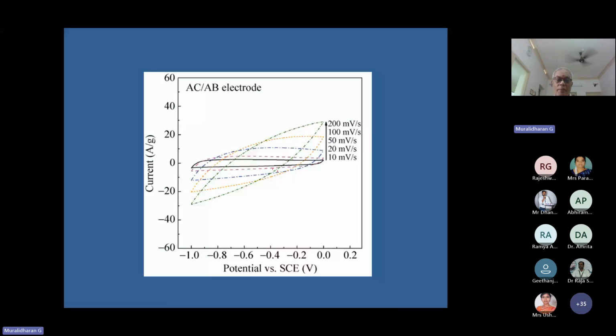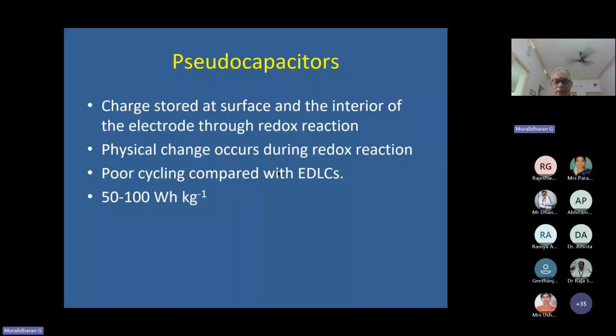When it comes to the pseudo capacitor, I told you it involves redox reactions. There is a physical change, and they don't last millions of cycles, but at least they last 10 to 20,000 cycles. In our laboratory, we made a pseudo capacitor which could last 10,000 cycles with 10% degradation. The degradation was very, very small, and they can store energies comparable to batteries.